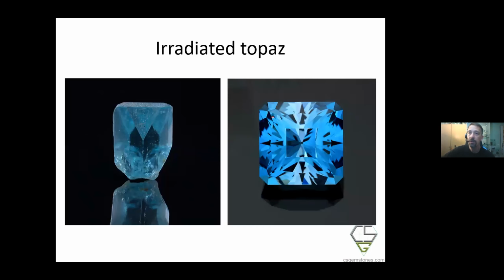Now, if we speak of color, we need to address the irradiated topaz. So this is a perfect example of what I think is a medium blue color. Very often you have these dark blue colors, which do look nice in small stones, but if you try to cut a larger stone, they look like a dark sapphire. So also irradiation does not produce the color that you like, but the color that the stone has more or less the history for. You can play a little bit around with the conditions of irradiation and heat treatment, but you will always have some stones that do not turn the color you like and some stones that do completely different things.